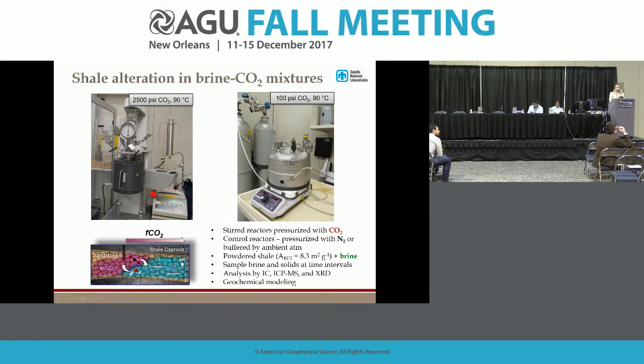We use stirred reactors. We use 2 types of reactors. One pressurized at high pressure of CO2, 2500 psi, and at those conditions CO2 exists as supercritical fluid. And then we use a low pressure reactor. Pressure is just 100 psi. And the reason for doing this, so here in the bottom I have an image of a CO2 plume. Conceptually, when you inject it close to the injection site, it's going to be supercritical, high pressure, high fugacity of CO2. And as you move away towards the edges of the plume, the fugacity is going to drop down. And fundamentally, the reactions are going to be different. It's not just the extent of reactions, but also products may be different as well. So we're examining those two regimes.